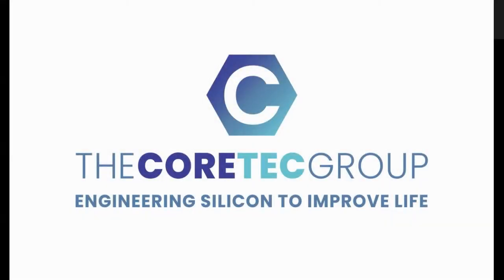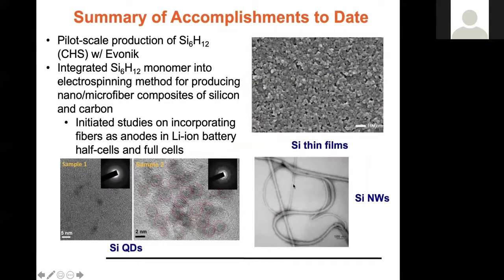So taking a look at some examples of materials that CHS has created in the past. A wide variety of silicon nanostructures can be made. So silicon quantum dots with well-controlled size, silicon thin films, with well-controlled not only particle size but packing into the thin film, so having appropriate voids in the thin film for wetting by electrolyte and things like that, as well as silicon nanowires.